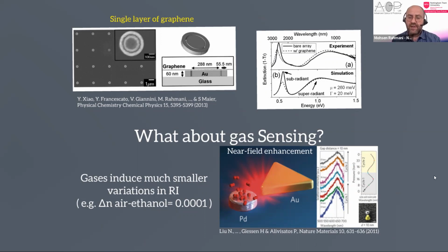Actually, it was 2011. So they used, again, this near field enhancement, but they used this palladium material that can absorb hydrogen gases. They put it right in the area of the near field enhancement, or hot spot, of these triangle gold nanoparticles. By shining the light and exciting this palladium, they can absorb the hydrogen, and then they change the overall optical properties of the cell, or of these nanostructures as a whole. By detecting those changes, you can detect the hydrogen gas around them.